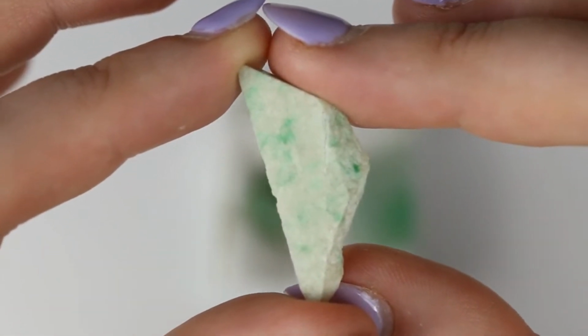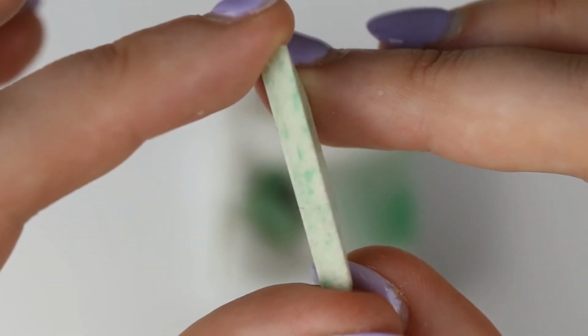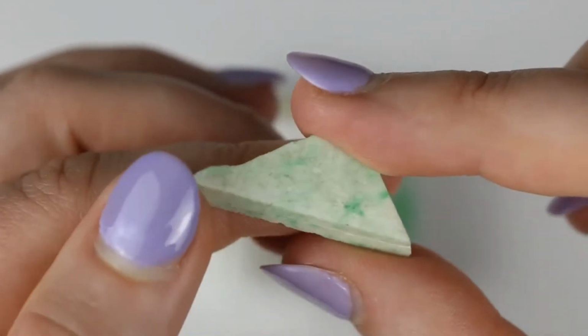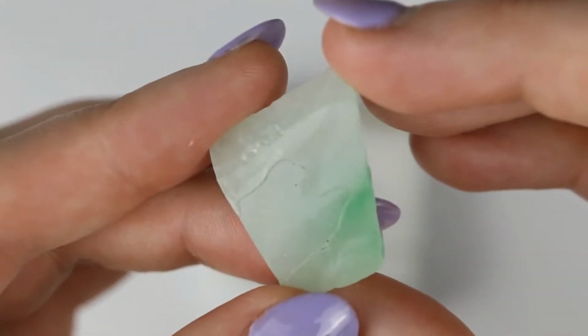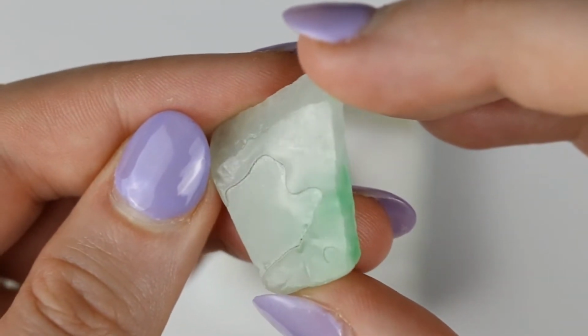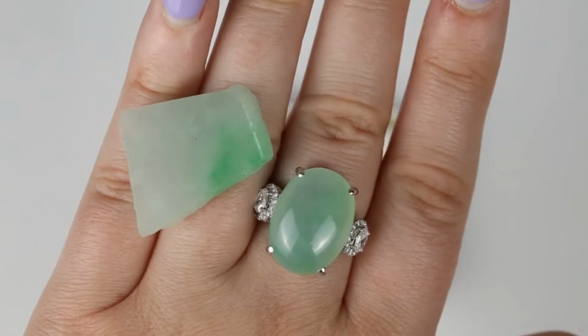This is low quality, crumbly, albeit genuine, jadeite jade that has been soaked in hydrochloric acid. So we call this jade bleached. Some jade is sold like this, but not often. Bleaching is usually a prerequisite for impregnation. This is low quality, genuine jadeite jade that was bleached, then impregnated with either polymer, wax, or resin using a centrifuge, forcing polymer into existing fractures and expanding them.